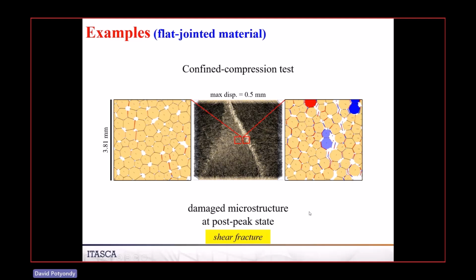Returning to the flat jointed material, now if you do test with some confinement on it, what you're getting in the specimen is a localization, which at the macro scale is a shear fracture, which is what you expect to get when you do a triaxial test with confinement. This is looking at just the material outside of the shear fracture region, right? And then this is looking at the material inside the shear fracture region. And you can see how it's moving, it's breaking apart. These colors represent what we call fragments.